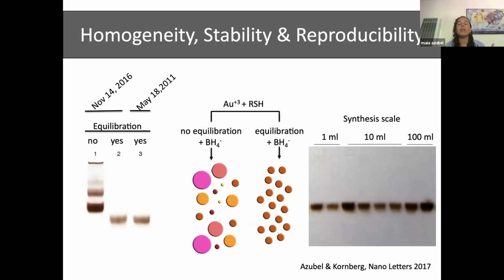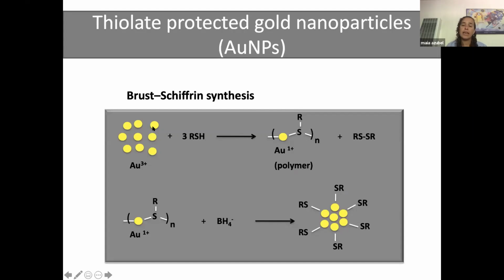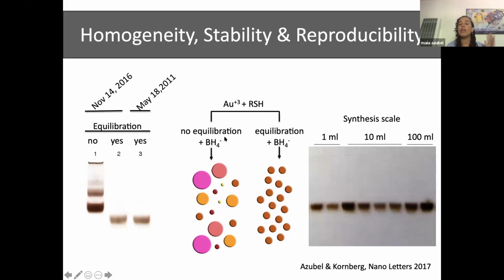So I was working on two fronts. The first one is, how do I get a synthesis that is very reproducible? And the first thing that I learned about that was, as I mentioned, there are two steps. If after this first step I don't let the solution equilibrate and I add the sodium borohydride, I get, as you can see here in the gel on the left, a lot of bands. This is the advantage of working with a water-soluble cluster: you can run it on a PAGE gel and you can see the different clusters. There are discrete sizes, but yet there are quite a lot of them. However, if I do an equilibration of the solution, then I get a very homogeneous product.